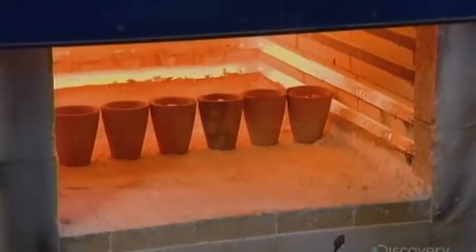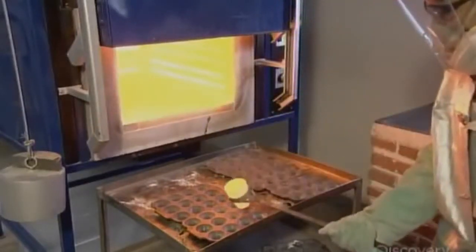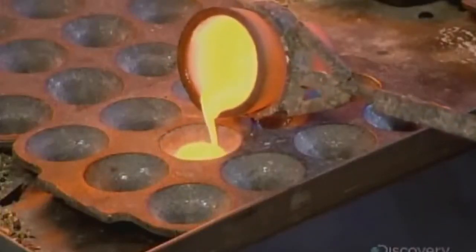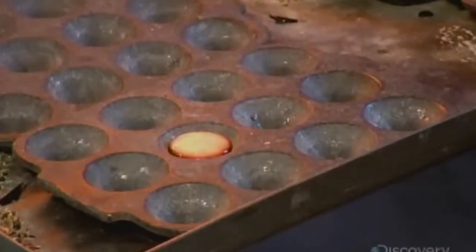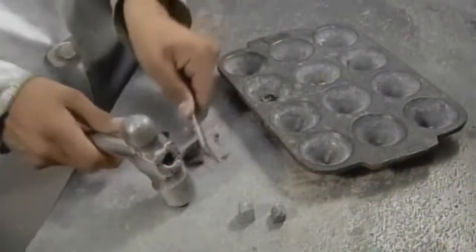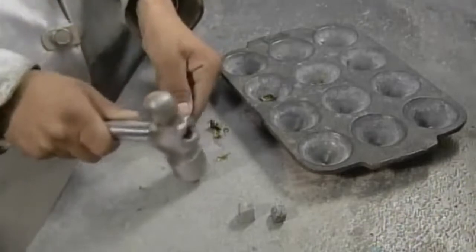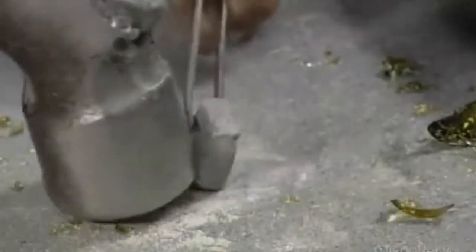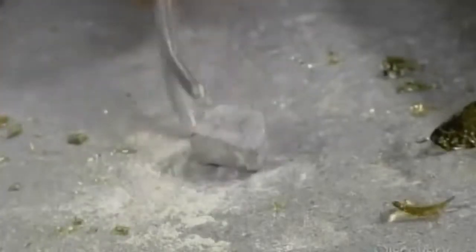In the mining company's lab, technicians continuously test ore samples to determine the grade, the term for the quantity of silver per kilogram of ore. They heat the samples to 1093 degrees Celsius for about an hour to burn off the impurities. What's left after the burn-off are the silver and other metals, such as lead, zinc, copper, selenium, and cadmium.